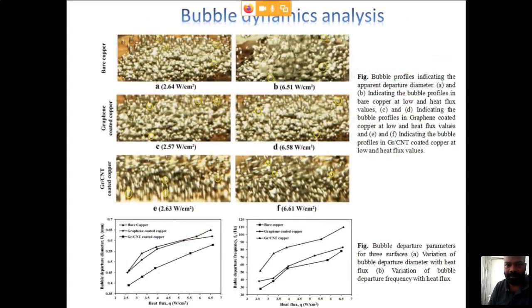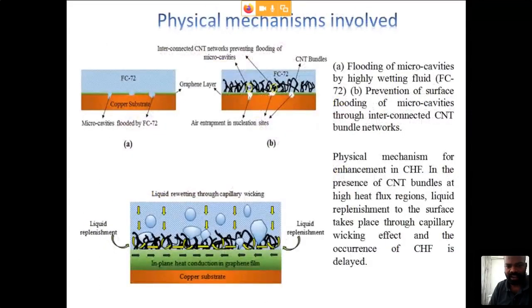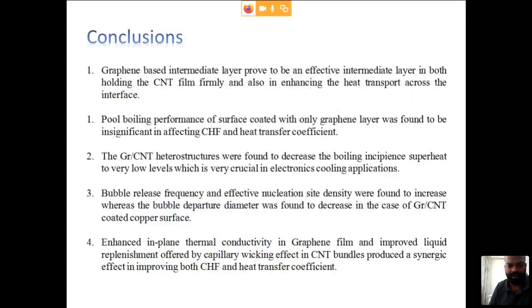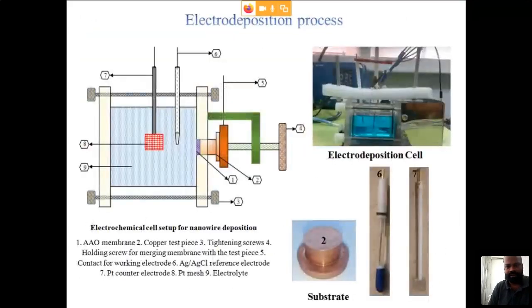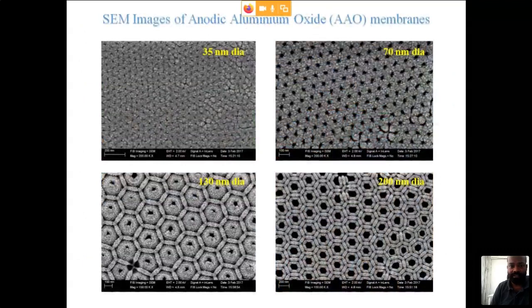Again, the basic bubble dynamic analysis. And this is the physical mechanism. So what happens to the liquid penetration and how the cavities are actually saved from flooding during this coating. Basic conclusion. And then we have used the electrodeposition technique to coat metal nanowires over this copper. And this is a template. This is the aluminum oxide template which we have used to grow this metal nanowire.